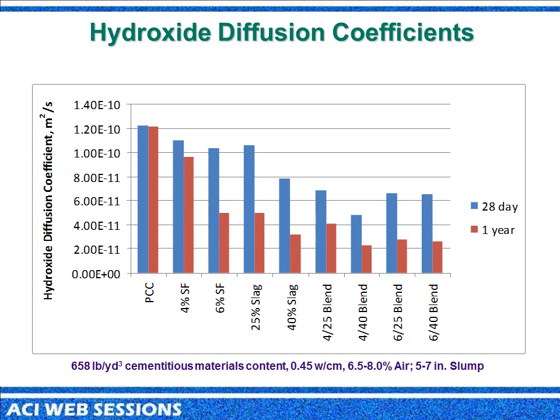When we look at the hydroxide diffusion coefficients, and these are coming from our Stadium modeling, we see something very similar. The similar trend is the Portland cement is really not changing very much at all. But very interesting enough is neither is the silica fume at 4%. So we can really see a change here when we start using our slag because of the long-term hydration that goes on using slag cement. So we're really starting to see that synergistic opportunity by using something like a silica fume, which will reduce permeability, but then at lower and higher blends, we're seeing even lower hydroxide contents. These were at 1-year data.